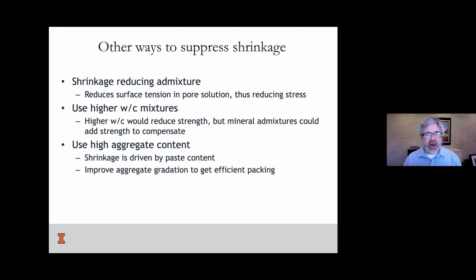Second, we could avoid all this self-desiccation, this chemical shrinkage problem, if we were not so low. Part of our problem is self-imposed. We're always driving concrete strengths to be so high and water cement ratios so very low. It's a problem that we beg for. We're creating concrete that is known to have this demand for water that we are not providing in the mix design. We shortchange the mix with regard to water, and hence this whole subject.